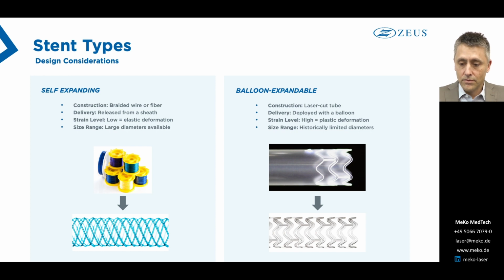Also, one very important difference, as we'll discuss later, is the strain level that the stent experiences when it's delivered. So for a braided stent, it's a very low strain level, which stays in the elastic region, and it gives that nice elastic pop out of the sheath. Whereas for a balloon expandable stent, the strain level is high because you have very localized strains. And that provides a plastic deformation, which we'll get into later is by design.